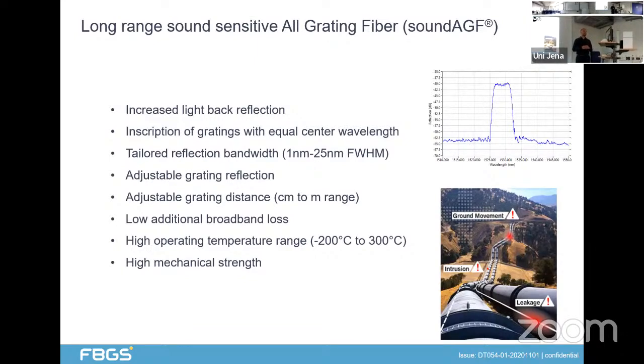For this method, usually different periods were not inscribed. Usually all gratings have the same wavelength, and depending on the system and application, the bandwidth will be tuned, usually in the range of 1 nanometer up to 25 nanometers, depending on the bandwidth of the source and also on the measurement device. That means for each system, the reflectivity needs to be adjusted. Reflectivities are in the range of 10 to the power of -5 up to about 1% per grating, and this can be done by tuning the inscription parameters during the inscription process.